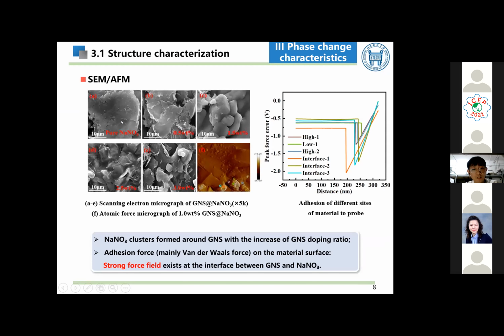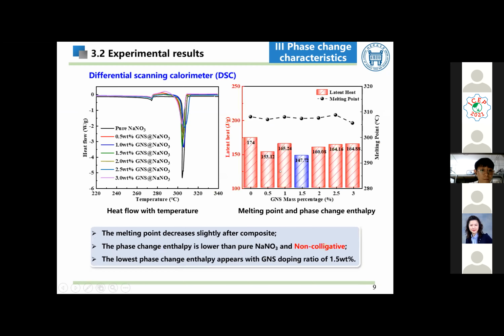The surface morphology of the composite materials was characterized firstly by scanning electron microscopy. As you can see, sodium nitrate clusters appear close to the nanosheets as the GNS doping ratio increases. At the same time, the adhesion force at different positions on the surface of the composites was measured by atomic force microscopy. As can be seen from the figure, the adhesion at the interface of GNS and sodium nitrate is obviously stronger than other positions, which means that strong force field exists at the interface.